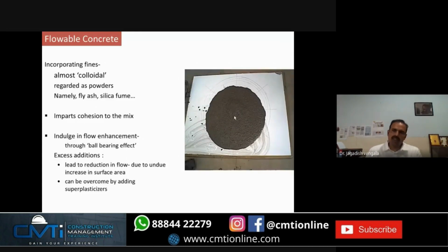As I mentioned, flowable concrete, as I showed, you cannot get by just adding water. But to get a homogeneous mix, you have to incorporate more fines. Suppose you have 100 particles, you have added water, there is excess water available. If you add another 50 particles, these 50 particles will accommodate the excess water, getting coated around it. So incorporating fines will reduce the bleeding or segregation, and it will enhance the cohesion of the mix. And flow enhancement can happen. But when you add excess, what will happen? It sticks or becomes more cohesive. Again, the problem of placing. So you have to see what should be the workability of your particular mix.